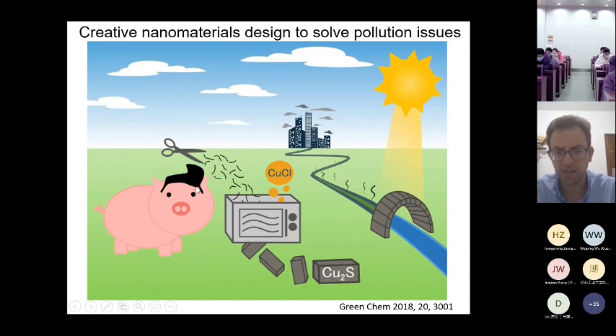So in essence, the concept was to combine the sulfur that is contained in the hair. I mean, in every single one of your hairs, we have a significant sulfur content from 1 to 5%. And with this significant sulfur content, we can actually extract this sulfur from the pig hairs and combine it with different metals. The combination with different metals, in particular copper, for the design of copper sulfide nanomaterials, allowed us to engineer this very useful photoactive material that could degrade different pollutants, including dyes, including phenolics, including antibiotics in wastewaters.